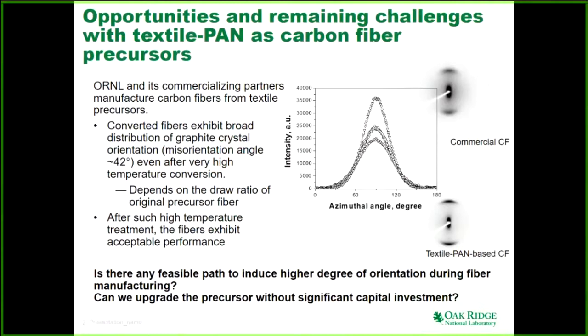That's how you improve the mechanical properties, and you might have heard that in carbon fiber manufacturing, we always talk about stretching, stretching, and stretching. If you can orient or align the carbon materials along the fiber axis, then your performance goes up. Another way of doing it is high temperature treatment. Still, in this method, look at the misorientation angle. Misorientation angle means how broadly the crystals are oriented relative to the fiber axis. If they're all oriented, then the misorientation angle is 0. That will not be the case, but some crystals are at a certain angle, and that can be on both sides. We take that angle, that cone, as the misorientation angle.